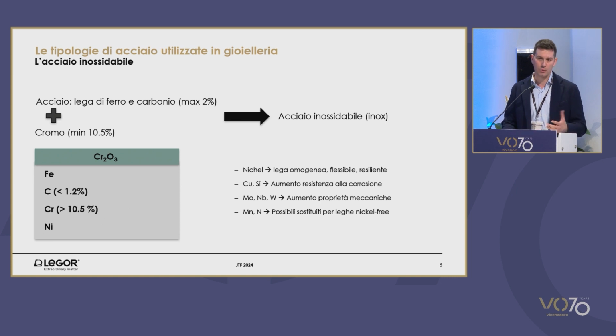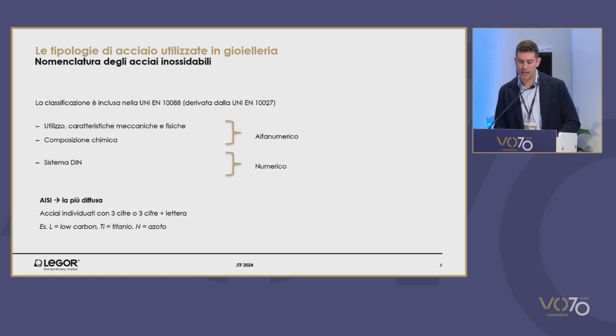Nickel, first and foremost. Nickel is actually included in all stainless steel with a percentage of up to 10%. It makes the alloy homogeneous, and it makes the alloy enjoy certain features such as resilience and flexibility. Other elements can be contained in lower percentages, not over 5%, granting certain additional features, for example, resistance to corrosion or hardness or other mechanical properties. There are stainless steel alloys that are nickel-free. Nickel is indeed replaced by manganese and nitrogen, but to date the performance is not satisfactory.